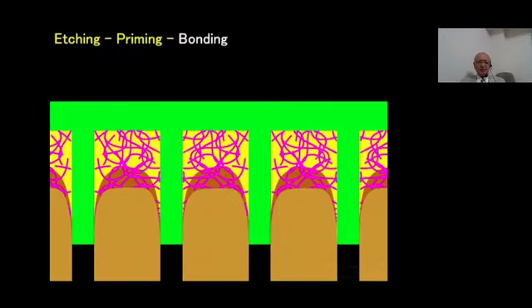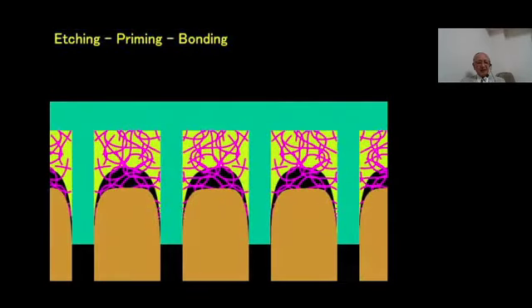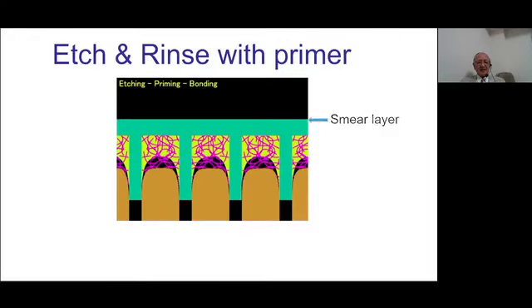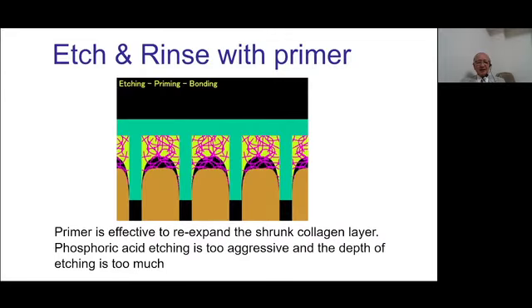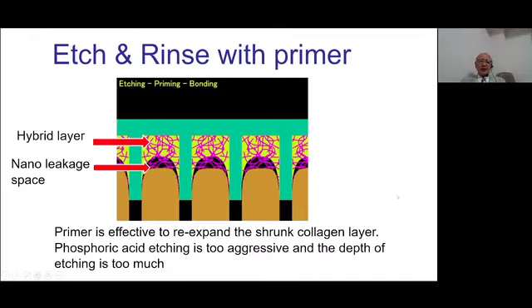However, unfortunately, the depth of the etching is too much. The phosphoric acid etching is too aggressive. That's why there is still naked collagen fibers at the bottom of the hybrid layer. This part is a very weak point of the bond interface. So that's why the durability of the bonding with etch and rinse technique, even with primer, was not so excellent.